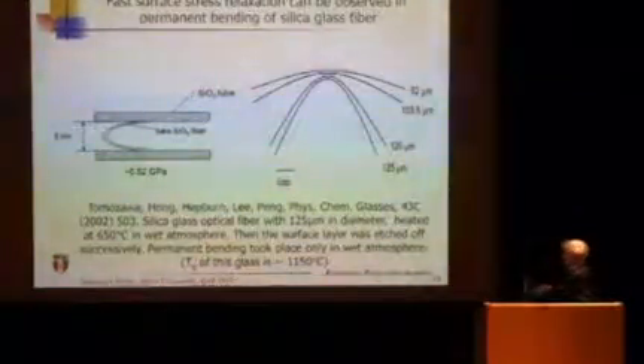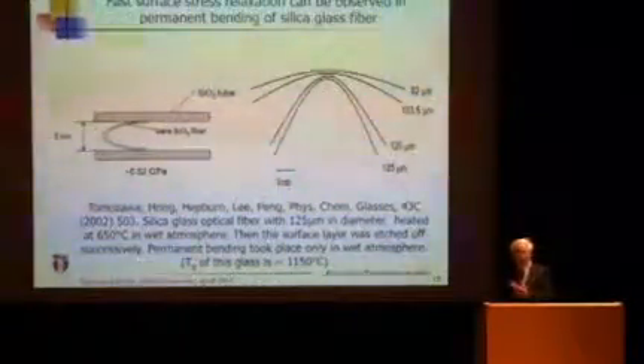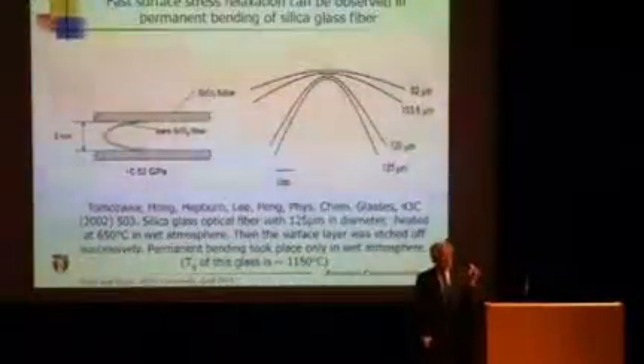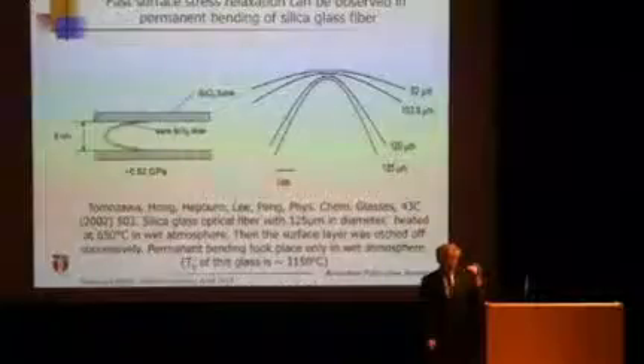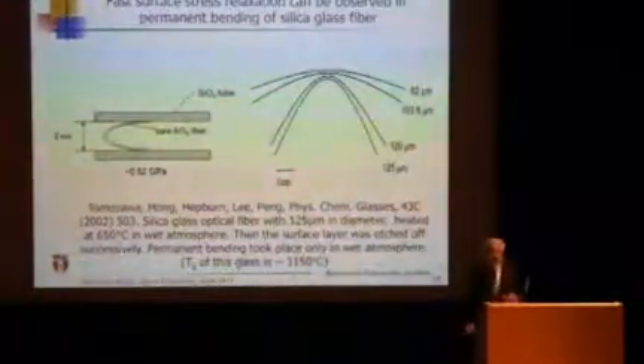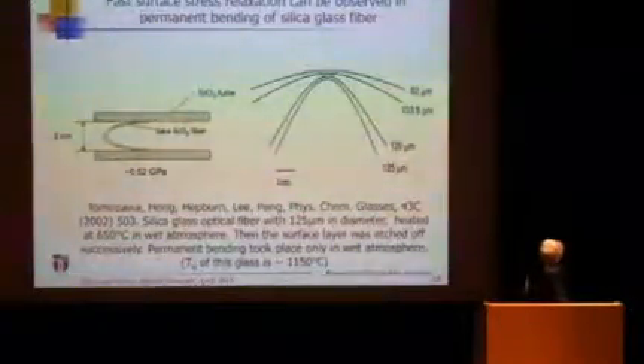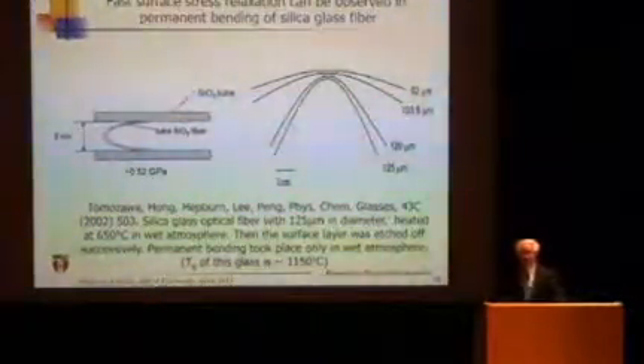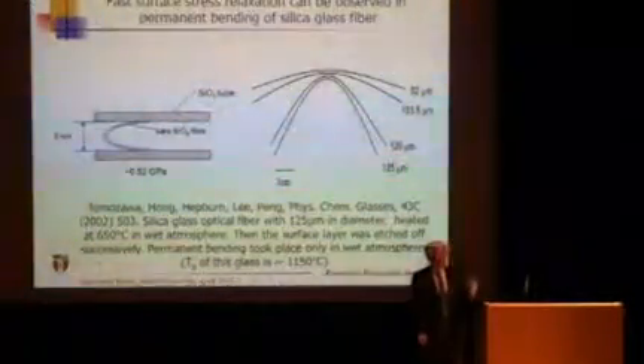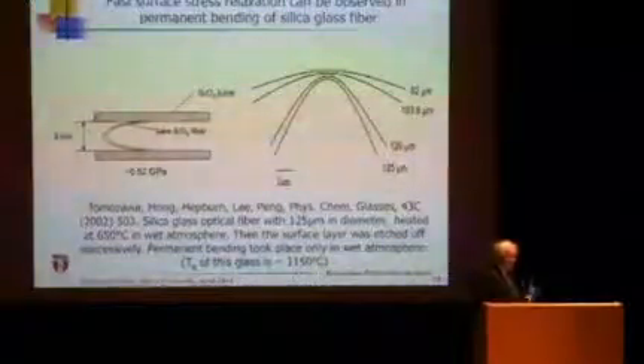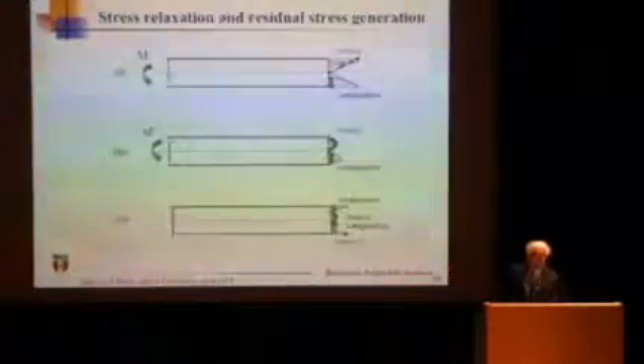Then we found the fiber is permanently bent. This was observed earlier by other people, but most of them thought this was viscous flow, that the entire fiber is bending. We felt this couldn't be, so we etched off the surface layer, and then it became straight, showing that only the surface is causing this permanent bend. And that must be due to surface stress relaxation.